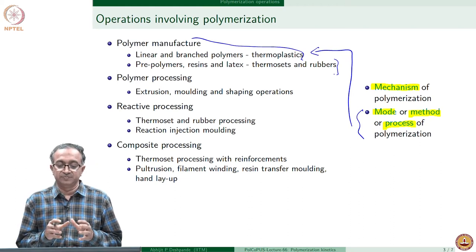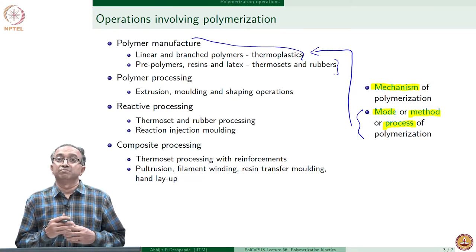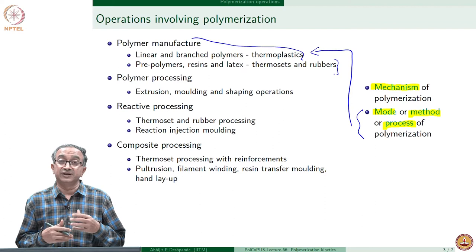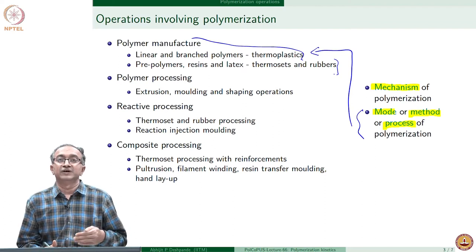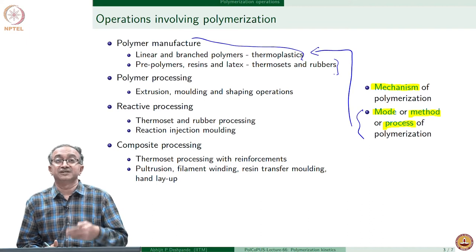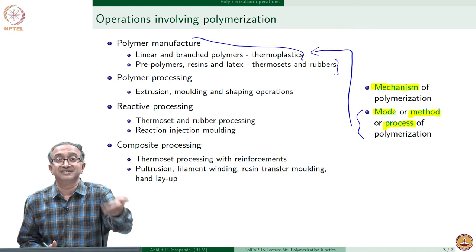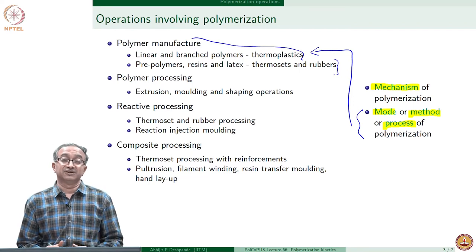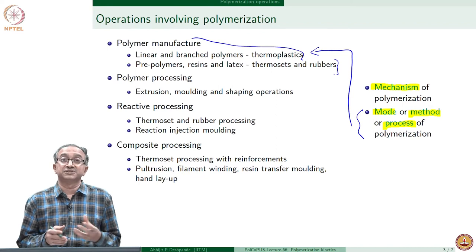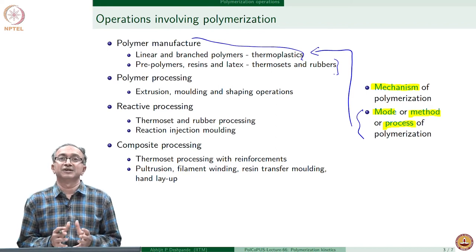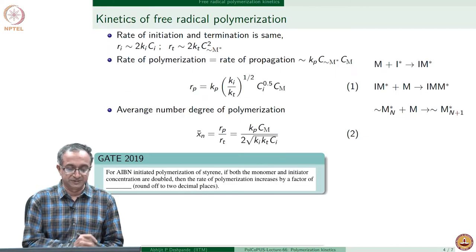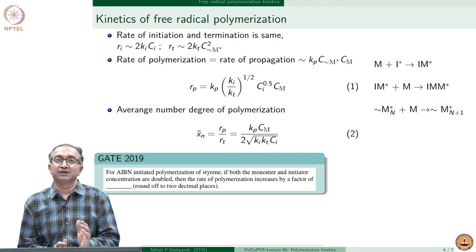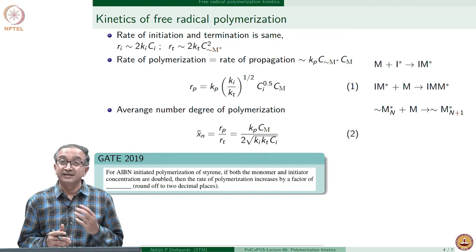We should recall that polymerization is essentially an exothermic process and a lot of heat is evolved. Management of this heat is important in terms of not getting to a stage where it is called a runaway reaction - because when polymerization happens temperature increases, temperature increase causes polymerization rate to increase, which increases temperature further. That is called a runaway reaction, where things can lead to degradation and combustion. Therefore, to avoid such things, this mode or method or process is very important because it can determine the stability of the overall polymerization operation. Let us now quickly look at the mechanisms and kinetics of polymerization.